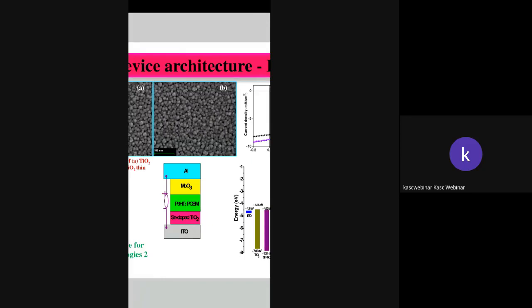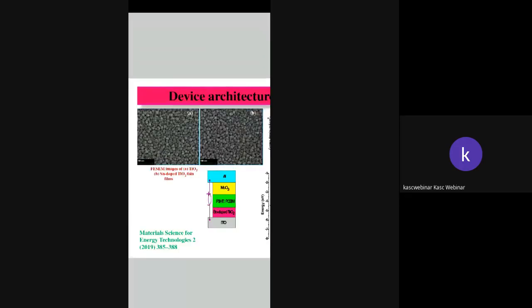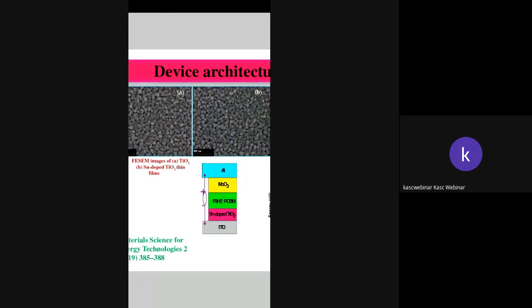And based on these aspects, we have fabricated the inverted organic solar cell, shortly mentioned as IOSC. Here you can see the same technique we have used to coat the TiO2 thin films. Here we have altered the technique as sol-gel spin coating method. Here the TiO2 thin films have been prepared by spin coating method. Earlier we have deposited TiO2 thin films by sol-gel dip coating method. And the same images of TiO2 and tin doped TiO2 thin films have been shown in figure A and B.